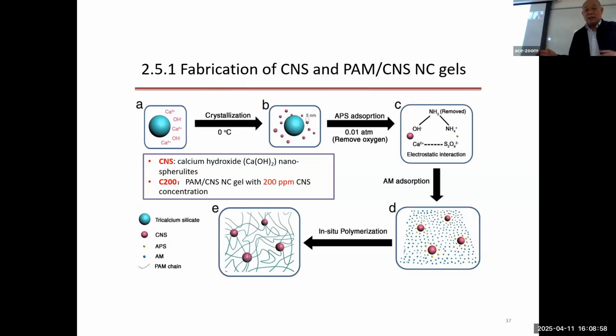First we did research to produce one kind of material called hydrogel. The hydrogel is basically a kind of polymer with water, about 80% water and about 15 to 20% polymer. Before the polymerization, we utilize the monomer and initiator, and we let them combine with the generated nanoparticles. And so we produce this kind of hydrogel.